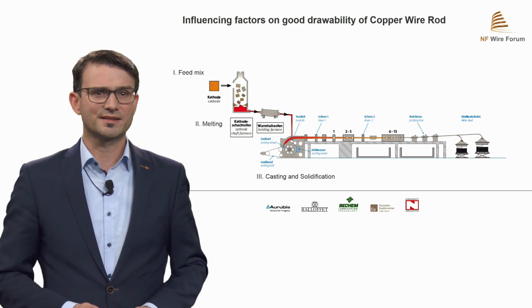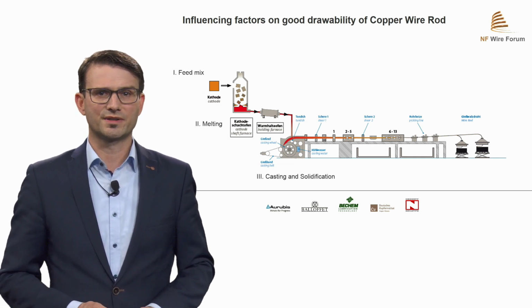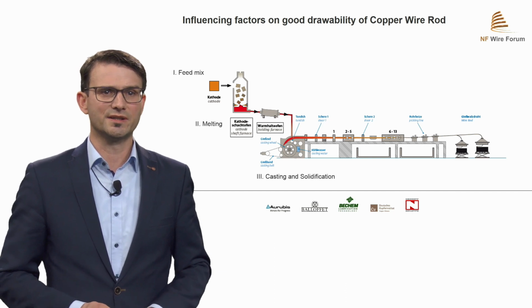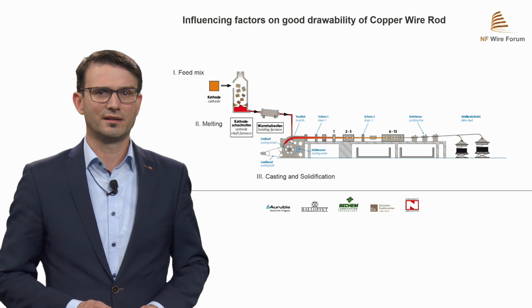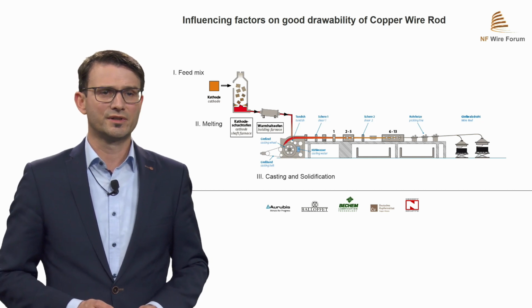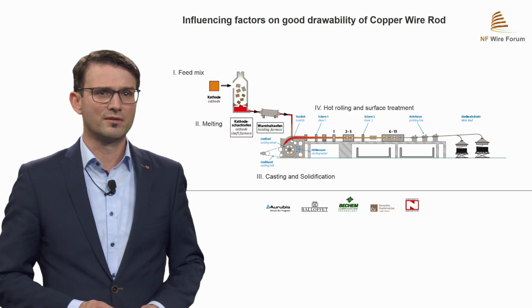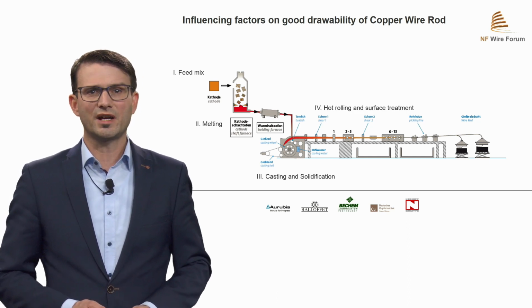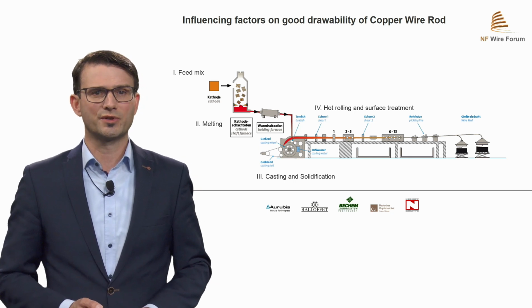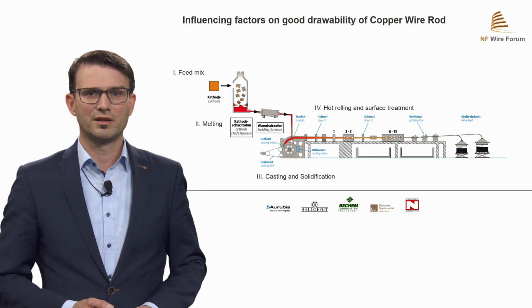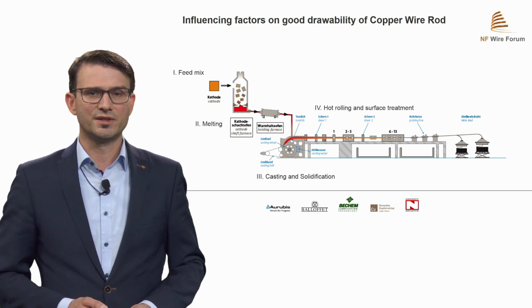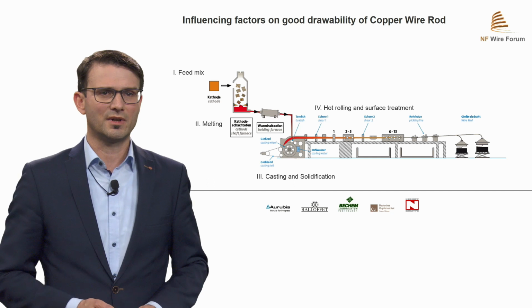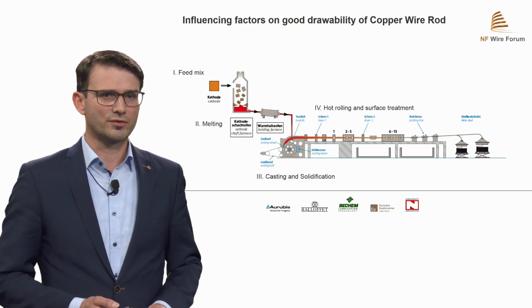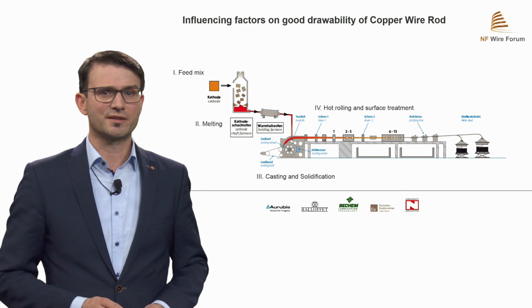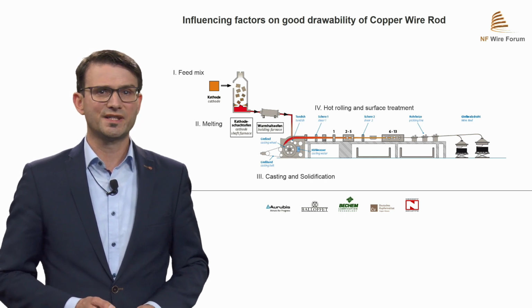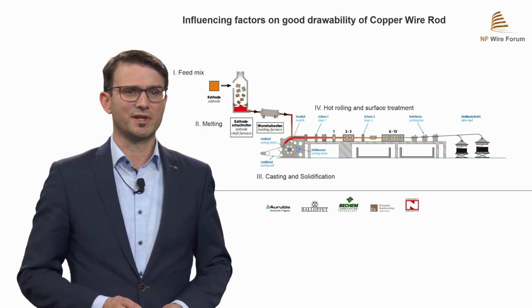Third, casting and solidification, the main area of interest to produce rod with outstanding drawing properties: homogeneous heat transfer, degassing, and constant growth of solid copper. Fourth, the rolling and surface treatment: reduction of the cross-section to gain mechanical properties to process the wire rod in cold drawing down to 0.1 millimeter or lower, and exclude iron inclusions. Fifth, the quality control: control of the product, the parameter sets of the line, and the required physical, chemical, and mechanical properties.